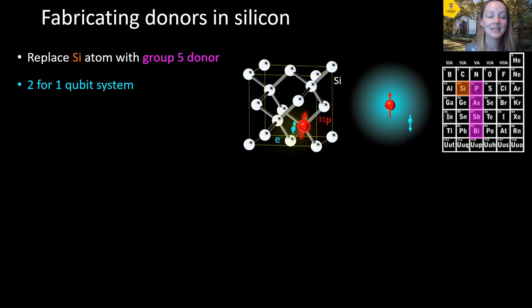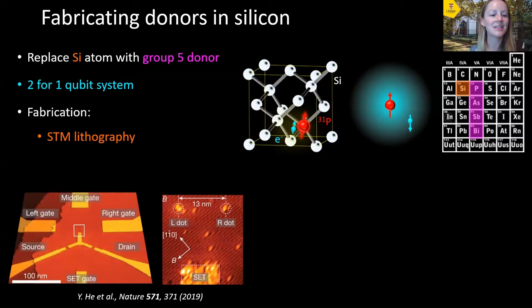And there's a couple of different ways that we can fabricate these donor spins, and I'll just go through them briefly now. So the first method is using a scanning tunneling microscope tip to pattern your silicon surface using a hydrogen resist, and you locally remove some hydrogen atoms from this surface, and then you incorporate a phosphine gas that will locally incorporate the phosphorus donors at exactly the sites that you want them to be defined by the STM. So in this way, you can incorporate the phosphorus donors into your silicon and then grow over with more silicon to encapsulate those phosphorus donors and then control them and read them out for your qubit system. And this is the work being done by Michelle Simmons at the University of New South Wales.